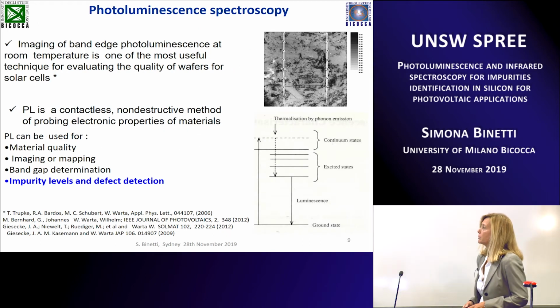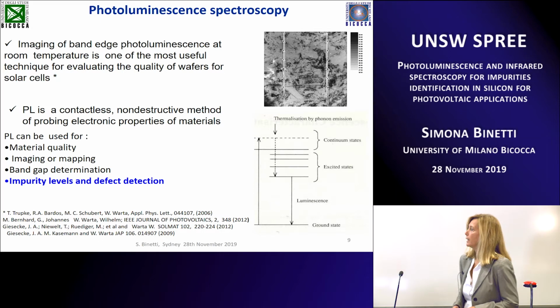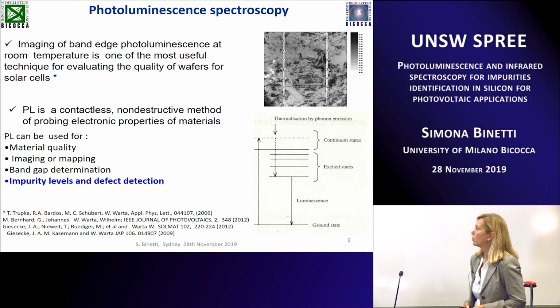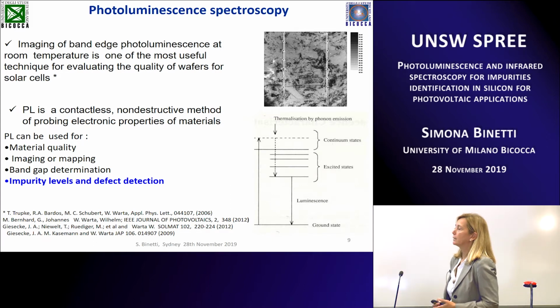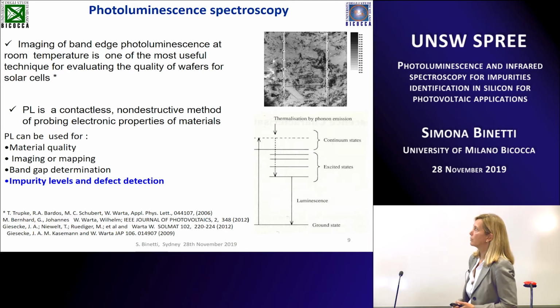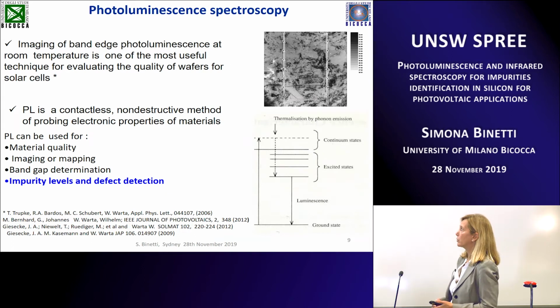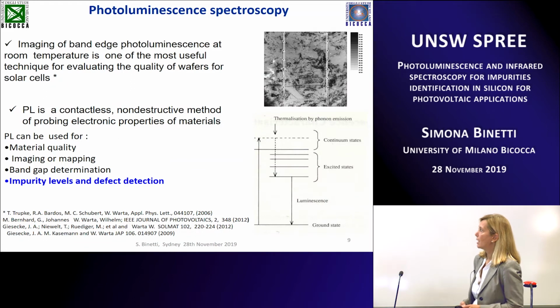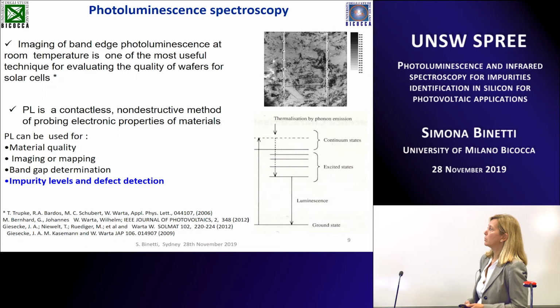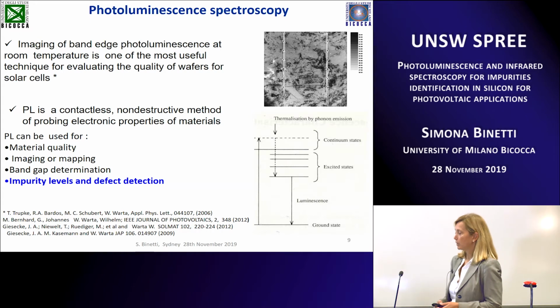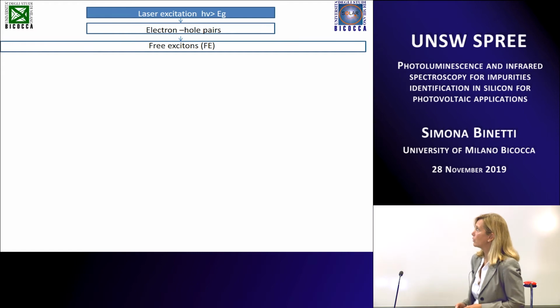So photoluminescence spectroscopy became very popular in the silicon field, thanks also to the work carried out by Trupke, co-worker in this center, because it's a very easy and fast technique to mapping the lifetime. It's a non-destructive method to map the lifetime and also the failure that you can have in a solar cell. But photoluminescence can be used also for detection of impurity level and defect information. So how it works?